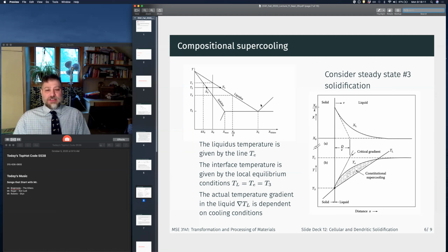The question basically was who feels they have enough of an understanding to explain this compositional supercooling? Okay, here's what I know from the reading. Compositional supercooling occurs when the temperature gradient of the solute entering the liquid is not very steep, when it's a nice slow gradient, which permits the dendritic growth. Yep. So when the gradient is slower than the critical gradient, which I'm pointing at right there, it strays into this region, which allows the growth of the dendritic solid, and thus the area where the solid is forming becomes supercooled.